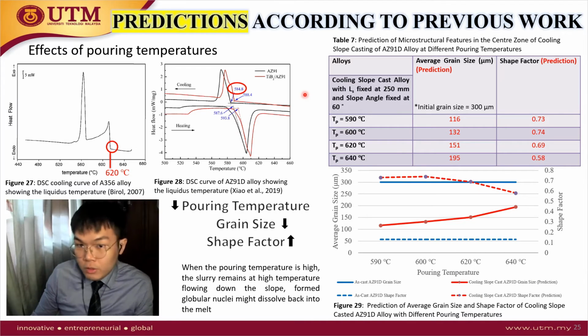To predict the outcome of cooling slope casting of magnesium alloy, first we need to determine the range of pouring temperature. We can't use the same pouring temperatures as in cooling slope casting of aluminum alloy, because different materials have different liquidus temperatures, and the pouring temperature is supposed to be slightly above the liquidus temperature to maintain a low superheat. We obtain the liquidus temperature of AZ91D magnesium alloy from the DSC curve, and apply a similar margin above it to get this range. We apply a similar percentage of reduction in grain size to predict the average grain size at different pouring temperatures, and the shape factor is assumed to be the same, presented graphically in figure 29.